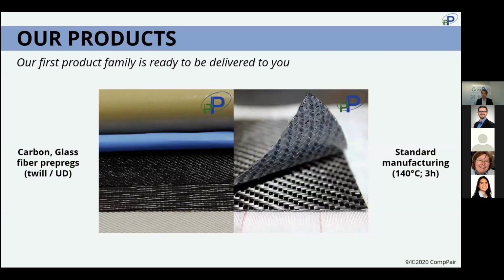With such technology, we are bringing now those prepreg products. This is the first product family that we have as carbon or glass fiber prepregs, pre-impregnated with one typical resin chemistry. And here I have an example of those prepregs that are twill or UD glass or carbon textiles. For you, what you have is a standard manufacturing that we are providing with this first family of product of 140 degrees for 3 hours.